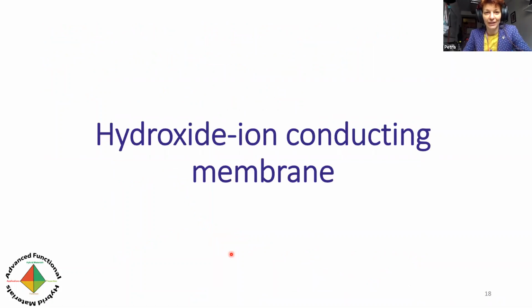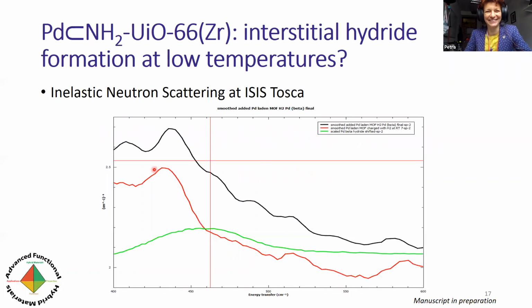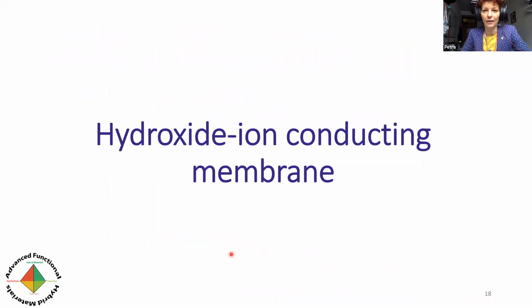And so with this, I would just like to quickly come back and say that indeed you could show that there is no hydride phase, and that is probably the reason for the particular catalytic properties, in particular the increased selectivity of our system. And potentially this may also be the reason for the increased lifetime or robustness of the catalysis.